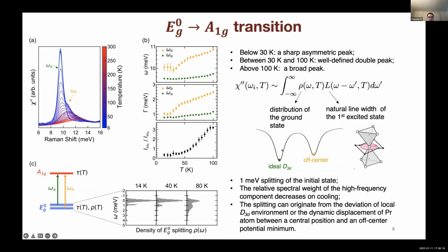The strong temperature dependence of the splitting cannot be simply explained by random disorder, and we suggest the origin of the splitting could be either the deviation of the local D3d geometry or the dynamic displacement of the praseodymium ion between a central position and an off-center local minimum. And this deviation or lattice dynamics is suppressed on cooling. At high temperature, the system prefers the off-center position.